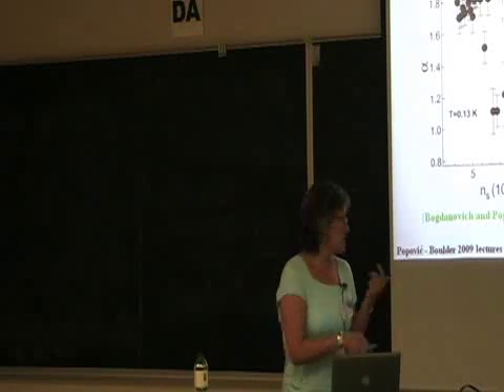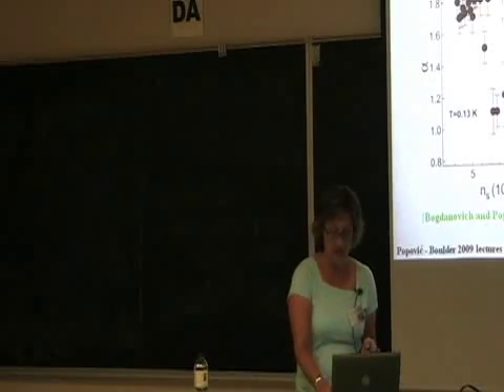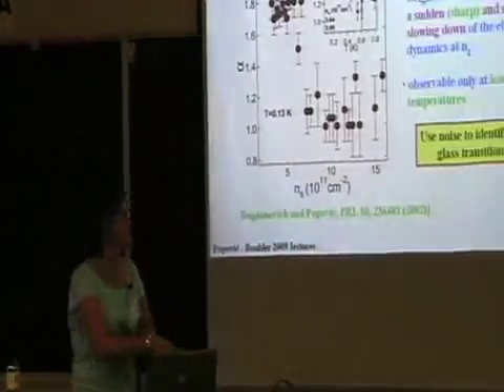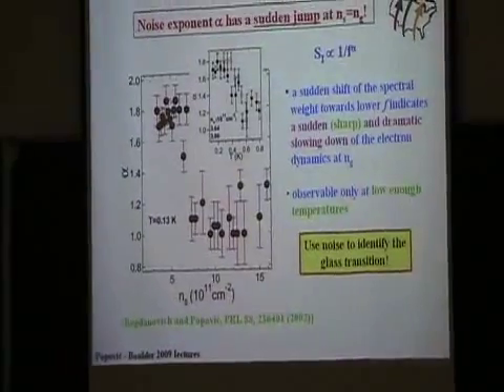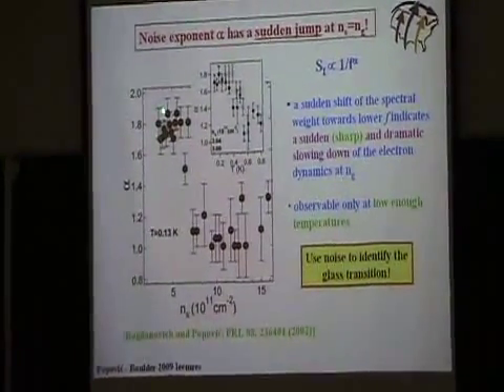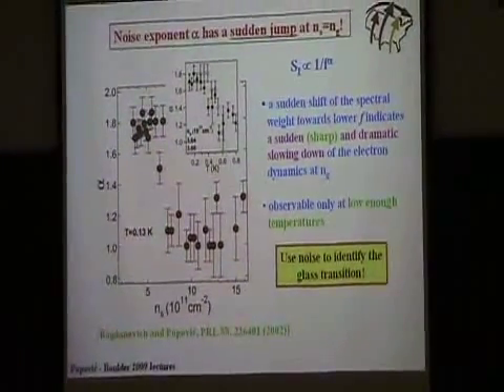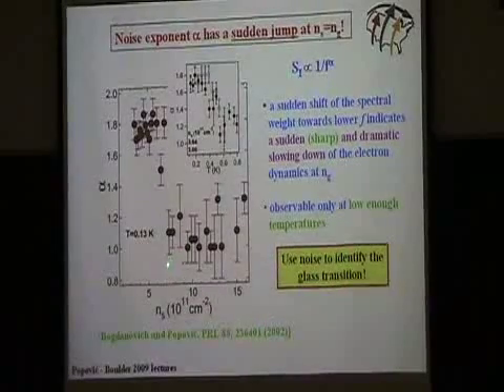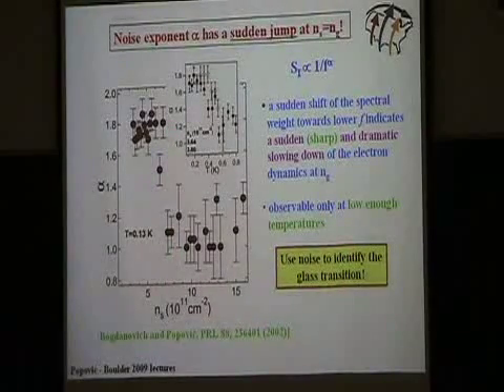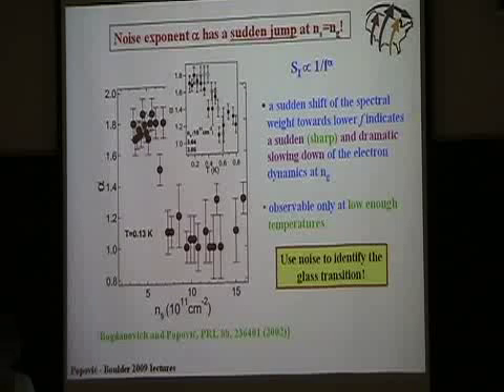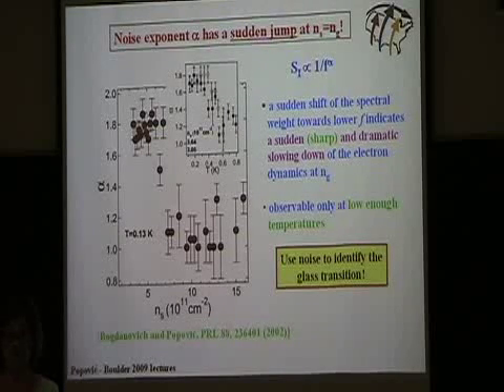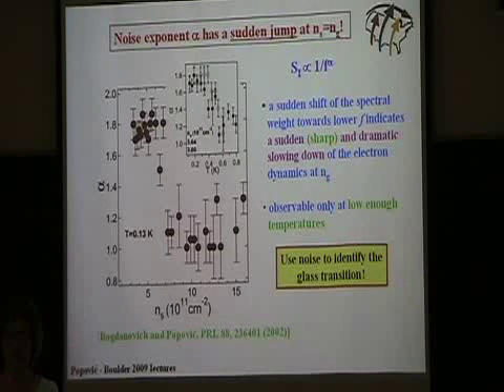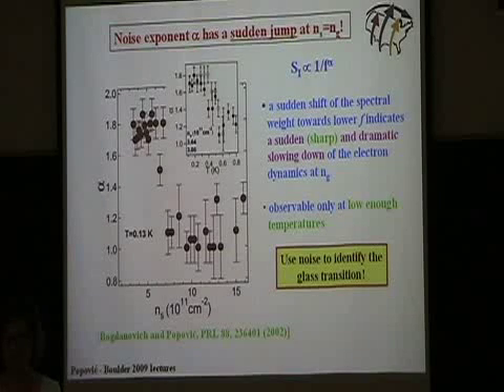Okay, so the dynamics obviously suddenly and dramatically slows down at Ng. So this shows us now, with what we know from yesterday, that we can use noise also to identify the glass transition, because this happens precisely at Ng. This is what we did in the measurements of high mobility samples with low disorder, because in those samples we have not done relaxation measurements. Okay, at least we have some data, but we haven't published them yet. They are getting old.